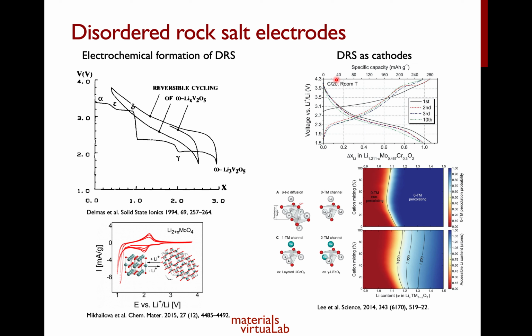So in 2014, Jinhyuk Lee, from Gerbrand Ceder's group, showed that when you have a lithium-excess disordered rock salt material, for example, Li1.2 molybdenum chromium oxide, you can charge and discharge this as a cathode with very, very large capacities, close to 300 milliamp hours per gram, right? Now, even more importantly, they showed that the reason why you can achieve such large capacities in these lithium-rich disordered rock salts is really due to what is known as a percolating network of zero transition metal channels.